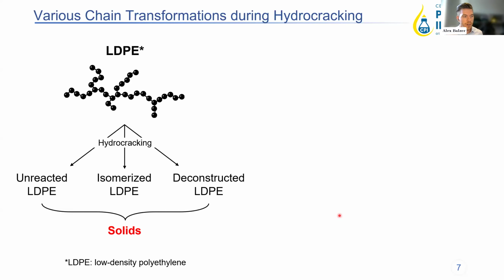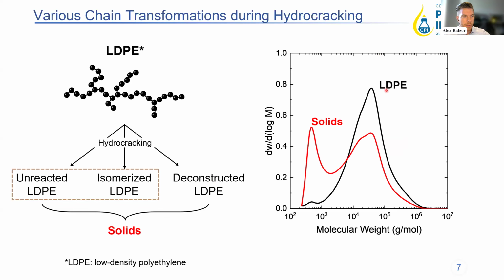And all three of these components make up that solids distribution. They're all just intermixed, and it's really difficult, nearly impossible, to actually separate all of these different chains from each other. So we needed a way to track all these transformations and how that affects the general process and interactions with the catalyst. What we did is we first looked at the unreacted and isomerized LDPE. What we notice from these two is that they're the same molecular weight, even though they have slightly different architecture. This poises them really well for gel permeation chromatography, high temperature GPC, where we can look at the molecular weight distribution of these materials, shown here on the right side, where the black curve is our neat LDPE, and the red solids curve is what we're getting out of that reactor.